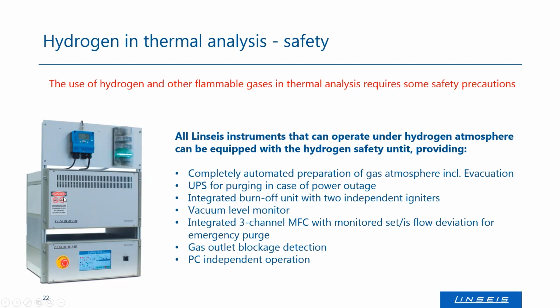it's a completely automated gas control, first of all. So it automatically can control the evacuation of your instrument and the filling with inert gas and of course with reactive gas. So this instrument is connected to a vacuum pump that evacuates your system, fills it with inert gas, evacuates again, fills it with reactive gas, which may be hydrogen, maybe anything else. Of course, you can also start an experiment in inert gas, heat it to a certain temperature, and then bring in the hydrogen or reactive gas, which can also be controlled by the automatic gas control here.